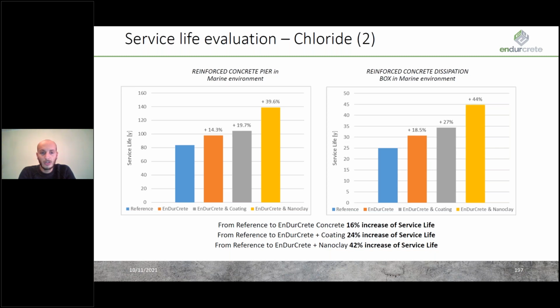And in these two different figures, we can see that the use of the materials described so far, like the EnDurCrete, and the coating developed during this project, and the EnDurCrete with the use of the nanoclay inhibitors, lead to an increase of the service life of both structures, with an average increase of 16% by the use of the EnDurCrete concrete. And we can go up to 24% using also the coating, and using the nanoclay inhibitors, we can have a huge increase, up to 42% increase of service life on average.